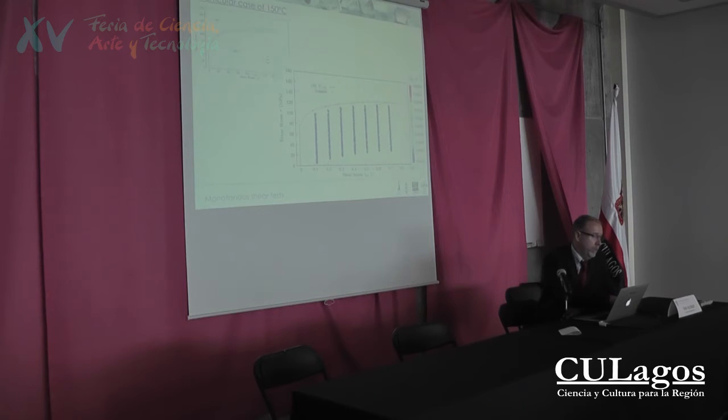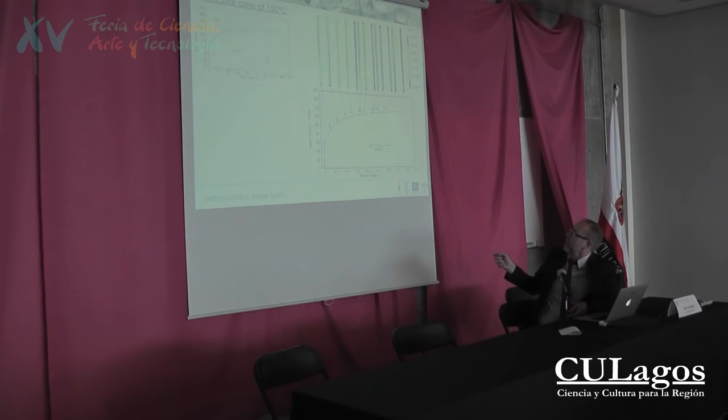And sometimes we don't have a PLC effect. You see, we have a homogeneous strain field, and sometimes we observe clearly some bands, even if the serrations are really small. So this test shows something that has never been seen before. At 150 degrees, you can also have the PLC effect, depending on whether you are able to investigate large deformation. This was not obtained before, so we are happy with this result.